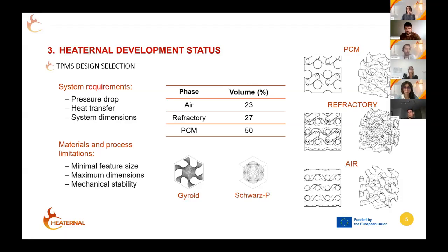Okay. On the other hand, there are also the materials and process limitations, which, for example, include the minimal printable size of the 3D printing, the maximum dimensions of the 3D printer, and the mechanical stability required by the material for it to be processed into the sintering stage and mixed with the metal or the PCM afterwards. Okay. In the current case, we have arrived at this solution, which involves a 23% air volume, 27% refractory, and a 50% PCM. You can see in the images on the right how those different phases are distributed in a 3D volume.